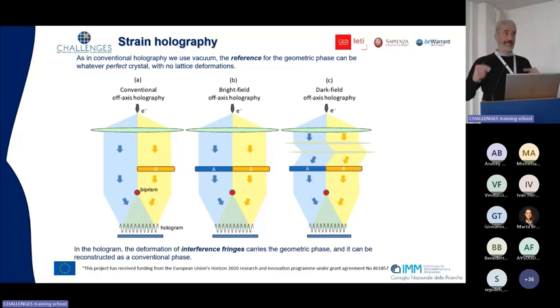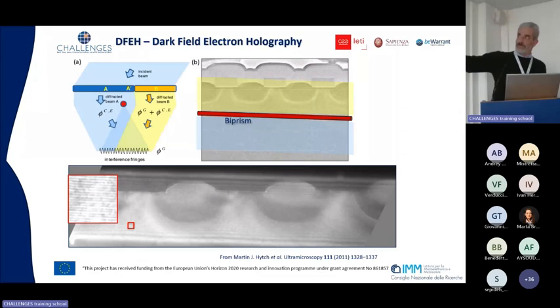But you cannot obtain any shift like this, because in this situation you are collecting the direct beam that carries only amplitude. We need a diffracted beam to reveal the phase. So we need to tilt our illumination to put the diffracted beam on axis and perform the same analysis. By doing this, it's possible to place a biprism like this. The region here is the reference silicon region. The upper region is a local structure, local oxide base. This is silicon, this is oxides, silicon oxide, and so on. And this is the strained region.